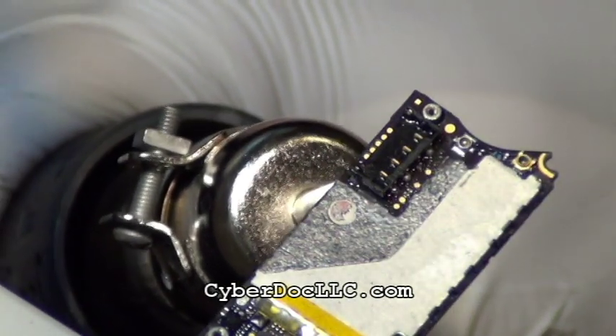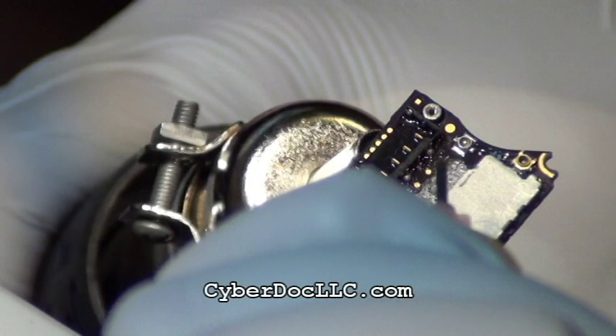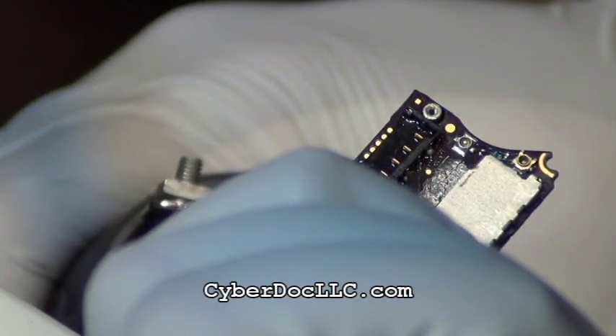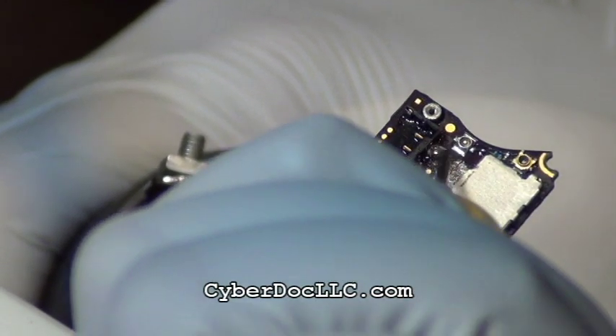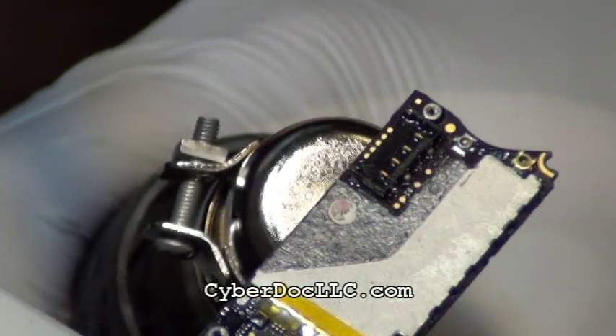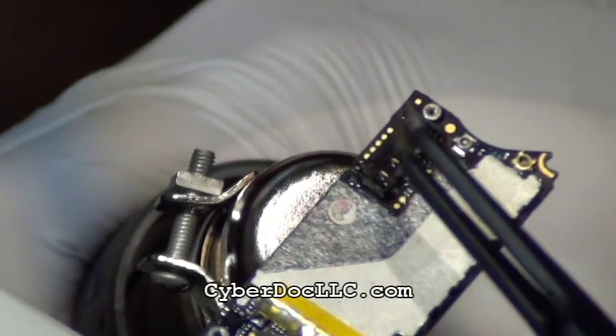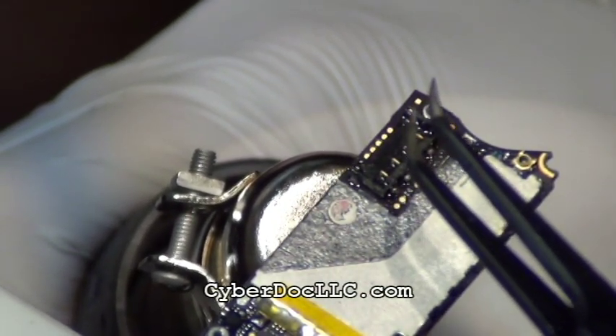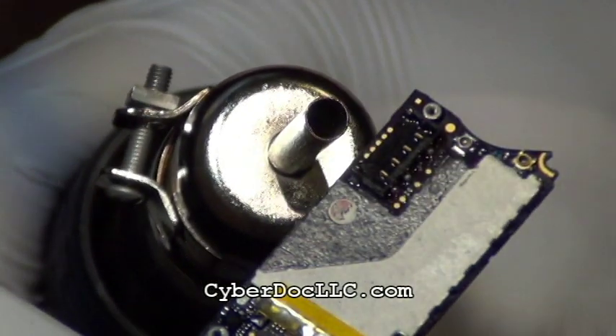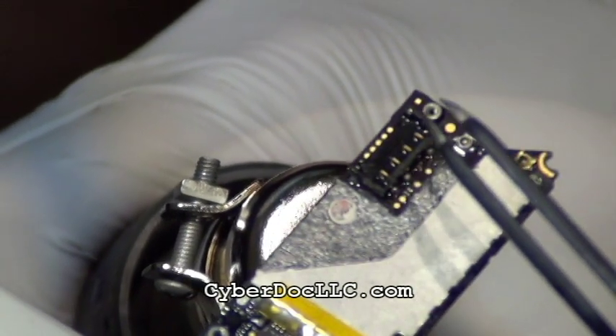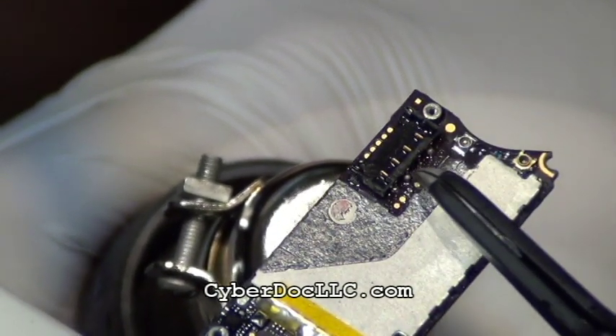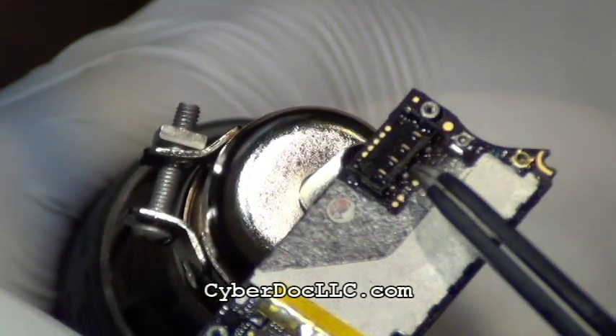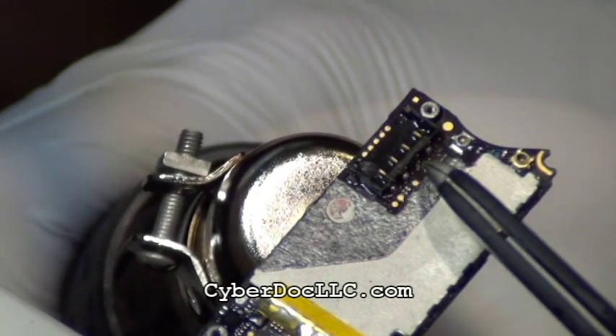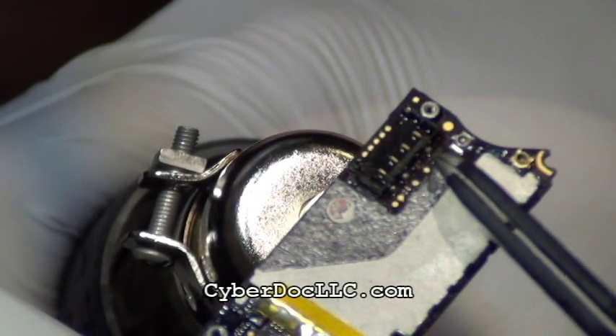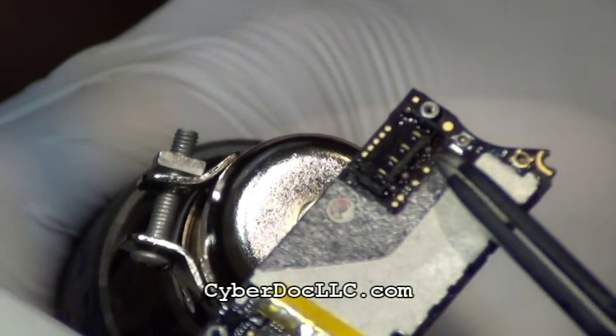So if you want to be absolutely safe with this, you can attach a thermocouple sensor right next to the area you're working on and measure the temperature there. But since I know this flux's boiling temperature, and I also know the solder paste I use has a low melting temperature of 137 degrees Celsius, if it's not melted, I know the temperature on the board is not anywhere near that amount. Hence it's really safe right now for the logic board, since I don't see smoke and I don't see molten solder.